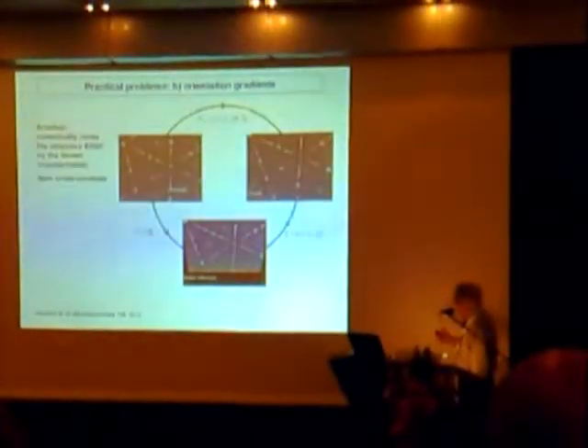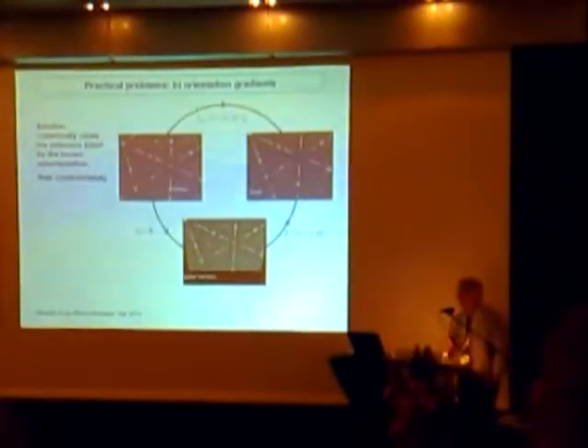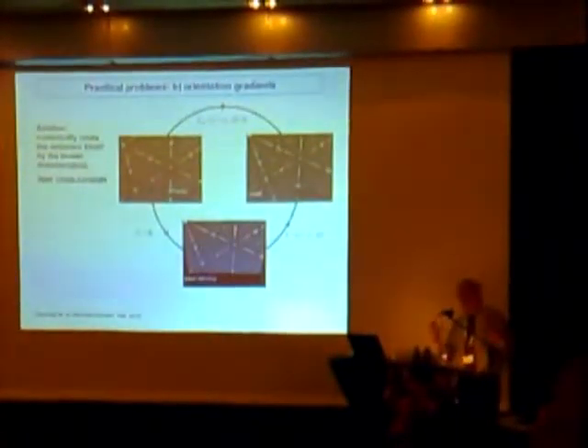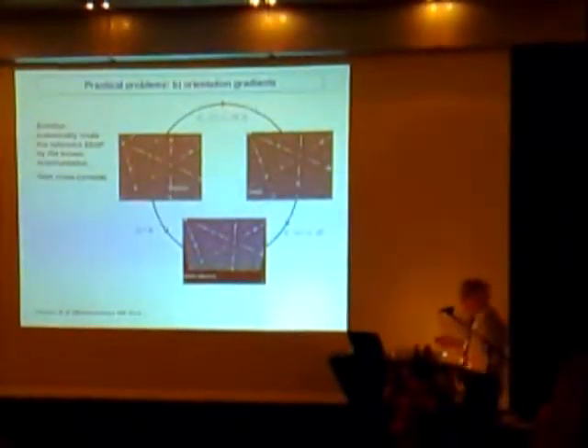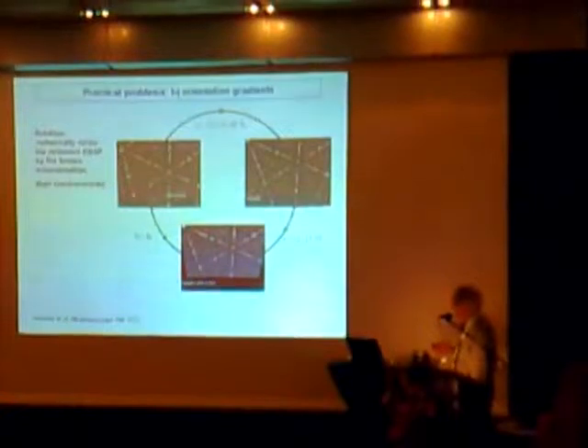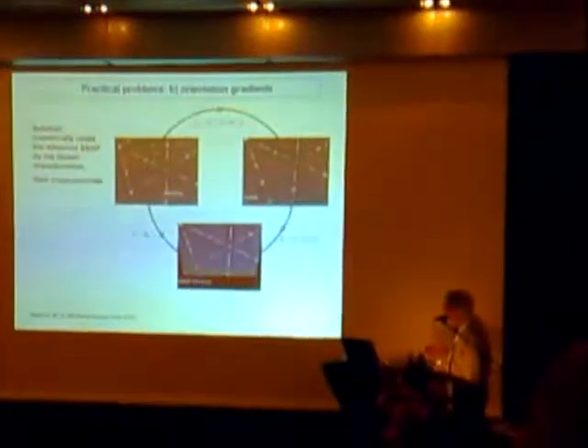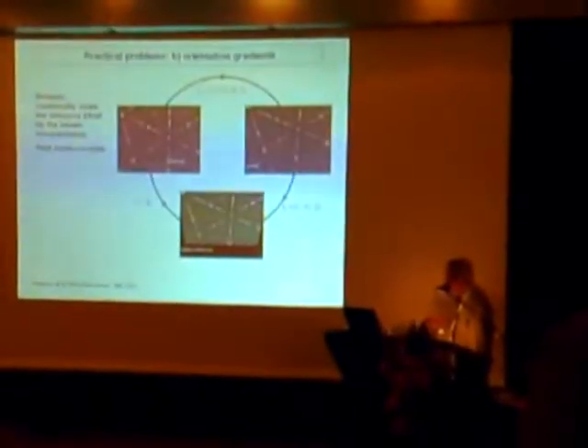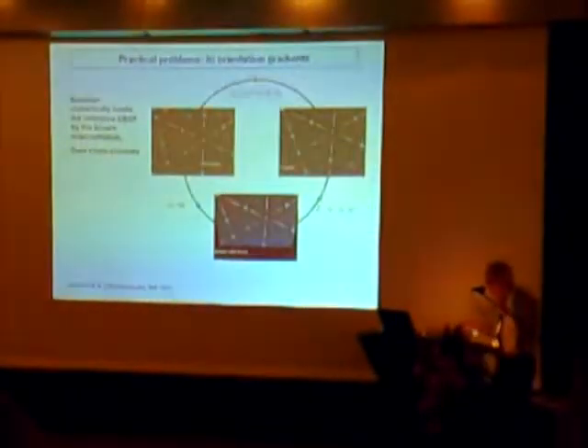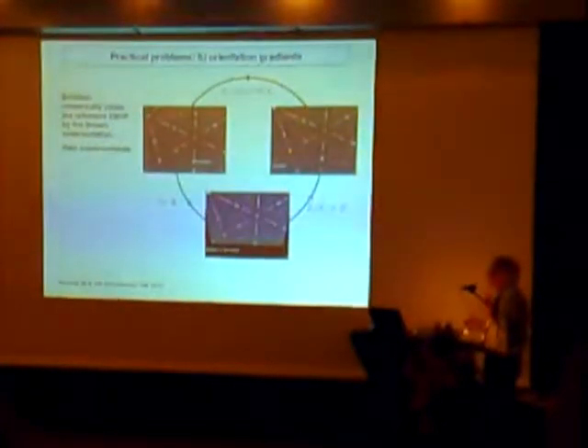For your reference, this is your reference pattern, this is, let's say, your current pattern. Between the two of them, you know what the rotation is, because this is a simple 2D transform. You know, it's 3 degrees around this and this, whatever. So you know the misorientation between here and here. What you can do then is rotate the reference by this known misorientation. So you apply a rotation on this pattern. In other words, you remap the entire pattern. Remember, you remapped it first for lens distortion. You remap it second now to correct for the rotation. And this is the rotated reference.